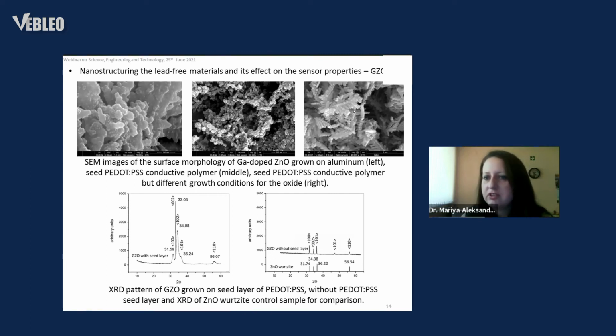formations are converted into nanoleaf formations with typical sizes ranging between 300 and 500 nanometers. It doesn't matter the concrete dimensions. Actually, in both cases, what is important is that the surface to volume ratio is increased, so it could result in, as you will see on the next slide, a triple increase